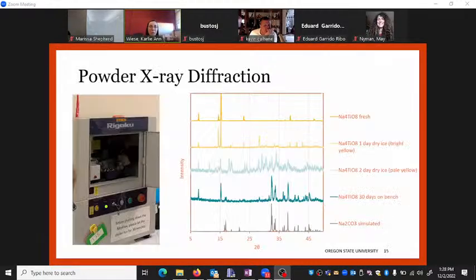And so to look more at the loss of crystallinity, one thing we do is use powder X-ray diffraction. So in the graph here, at the top, there are really nice sharp peaks that we get when we collect this data. And these clean sharp peaks are indicative that this is a really crystalline sample. So this is the fresh sample. And then going down, we see that the sample is getting a little bit noisier. It's looking a little bit more chaotic. The peaks aren't so nice and sharp. And so we're seeing some loss in the crystallinity. That's what that's telling us.